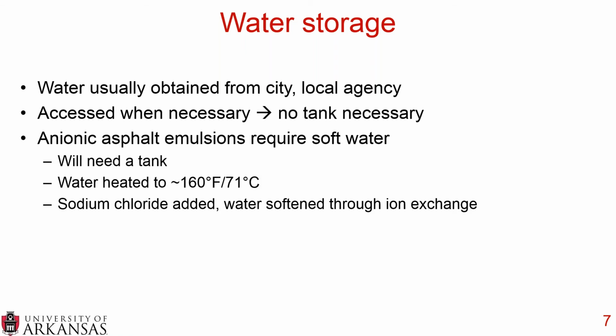The only common exception to that is if you are making an anionic asphalt emulsion, because anionic asphalt emulsions do require soft water. So if your area has hard water, you will need a tank. You need to heat that water up to about 160 degrees Fahrenheit, and then you add some sodium chloride, and that softens the water through an ion exchange.